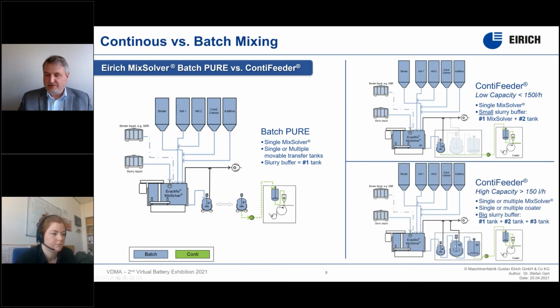This is the reason why we put in some more buffer tanks, so that we discharge a batch, we can qualify the batch, we can take samples and analyze them in a lab, or we can analyze it inline with sensors, then transfer the qualified batch into a buffer tank. From the buffer tank, we then transfer it to another buffer tank, which is usually just a stirred tank without cooling, without vacuum, to provide enough slurry in a continuous way to the coating line.